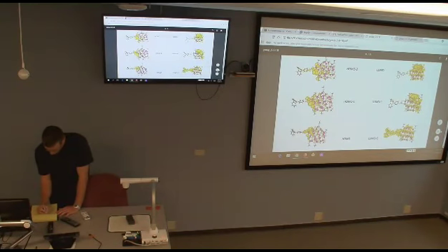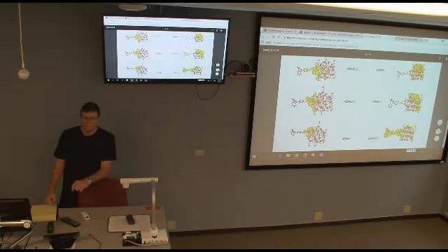reduced model where you completely detach the dye but leave the linkage group, right? And again, you can do it with proton and without proton, meaning again, with charge and without charge. And by the way, it would also be interesting, if you have just a carboxylic group without the dye and without proton, with a negative charge, would you see the orbital sitting on these carboxylic groups? Our Gaussian calculations with a single carboxylic group or all carboxylic groups do not show localization on a carboxyl. Carboxyl is not really contributing to the HOMO-LUMO gap, same as amides do not, right? But this would be interesting to check.